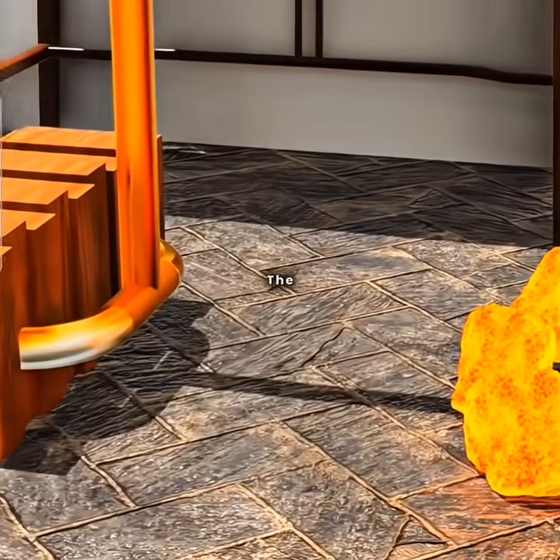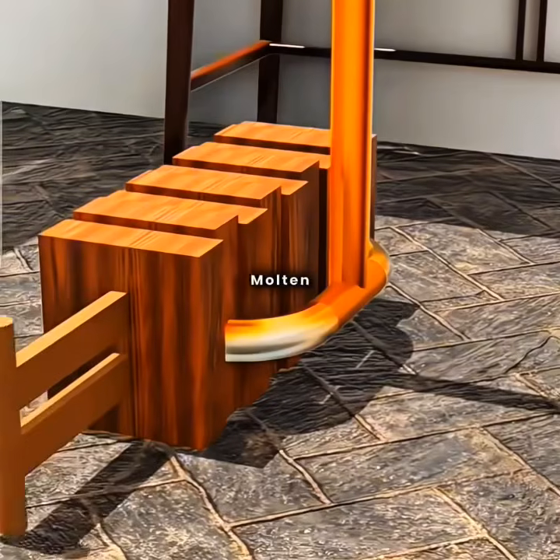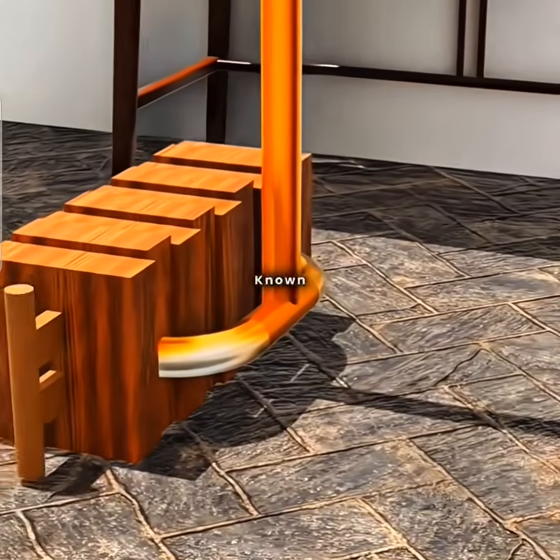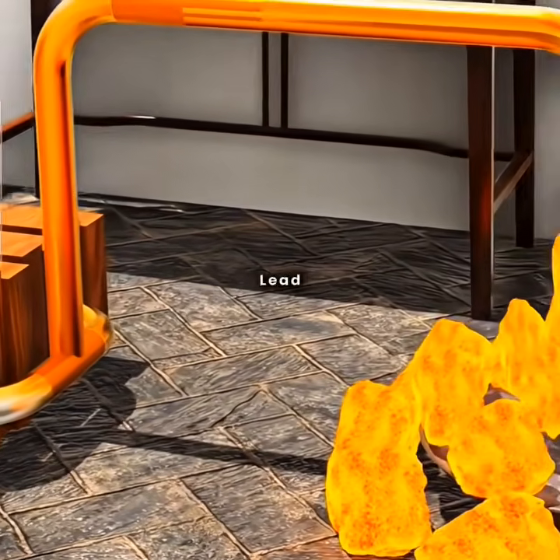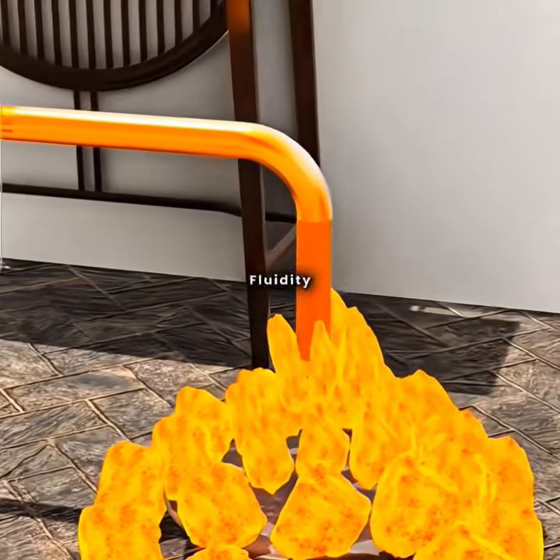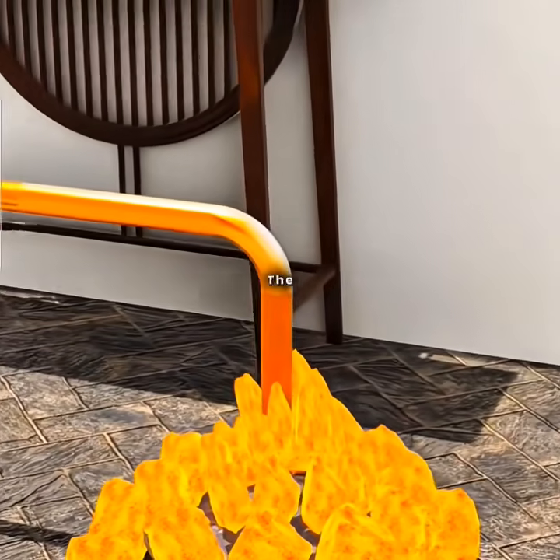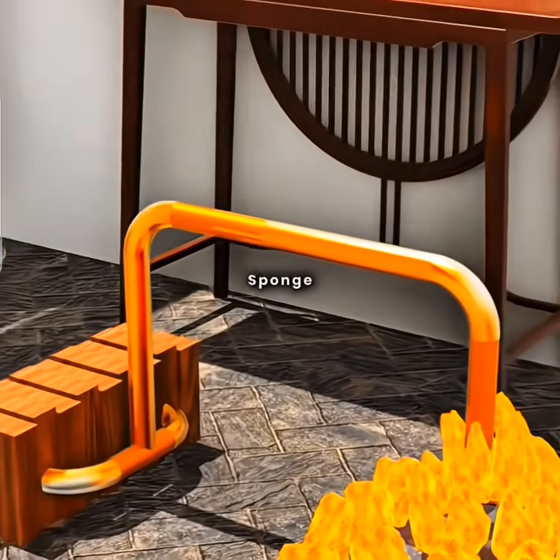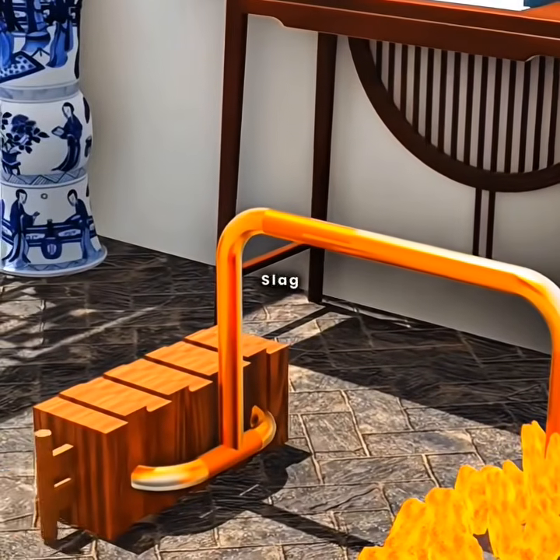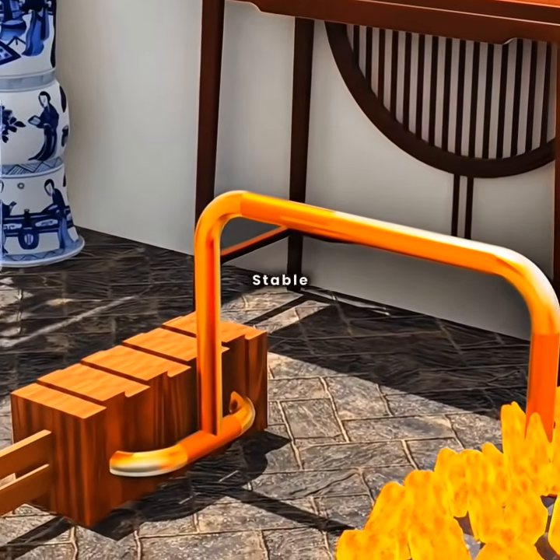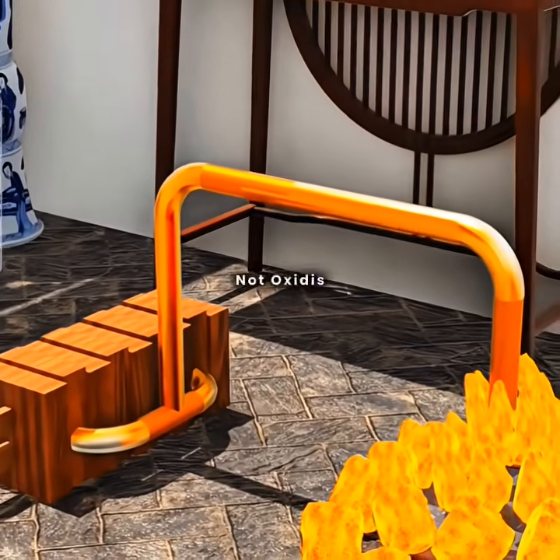a molten state. The air from the blower oxidizes the molten lead, generating lead oxide, known as litharge, and the liquid lead oxide, due to its weight and fluidity, is completely absorbed by the porous bone ash bed like a sponge, or blown to the edges as slag. As for gold, because of its stable nature, it withstands fire and is not oxidized.